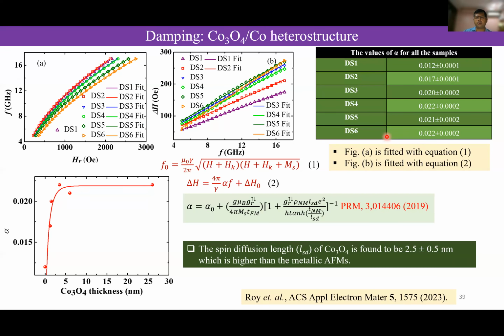I'm just summing up, where I would like to show that nice spin pumping has been observed, and the spin Hall angle is very much comparable to platinum. So it shows that Co3O4 is a very interesting material.